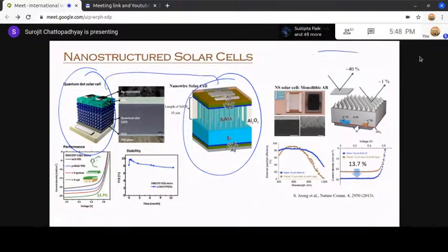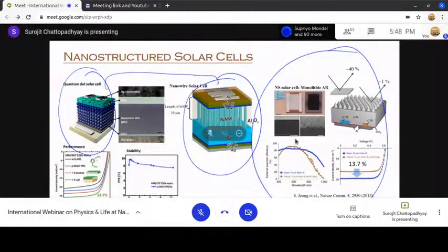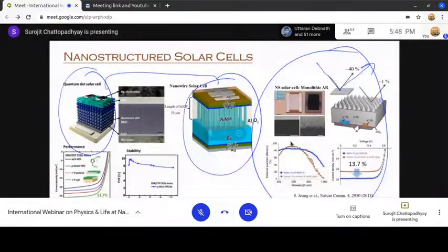The picture on the right that you see here has a completely different purpose. Normally, when we make solar cells out of thin films, like amorphous silicon thin film solar cells, or even p-n junction crystalline silicon solar cells, when you shine sunlight, nearly 40% is reflected back. That means you are losing 40% of sunlight. But we can't do that. We want to make the most of it. Available sunlight is there.